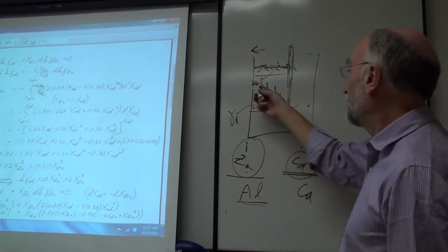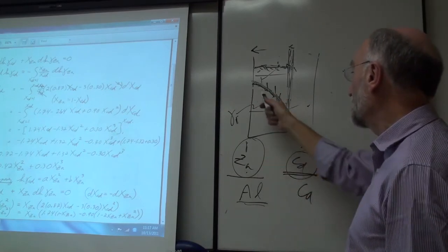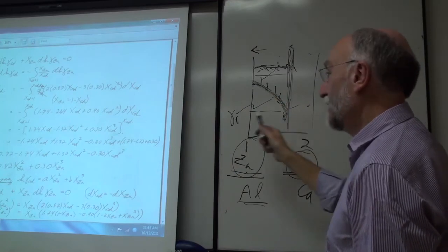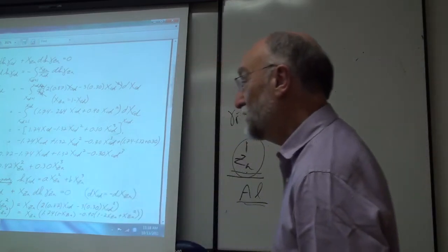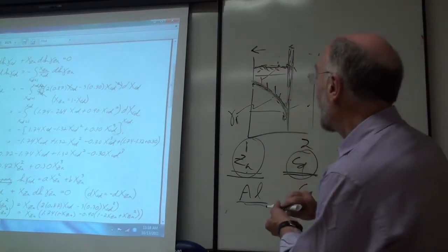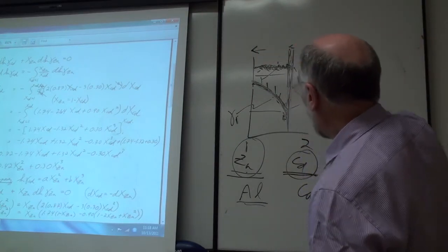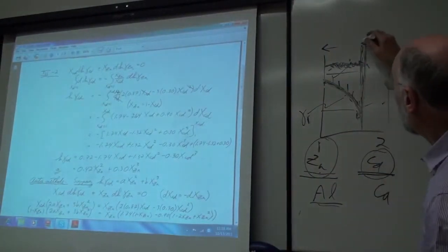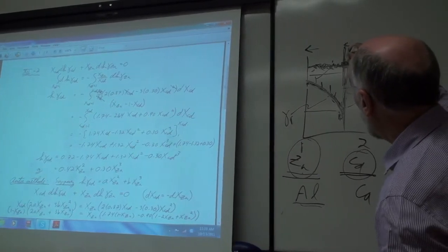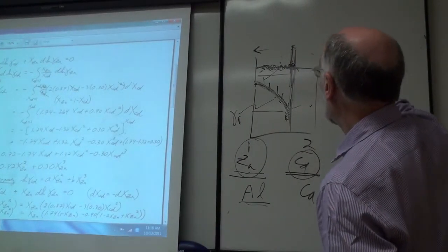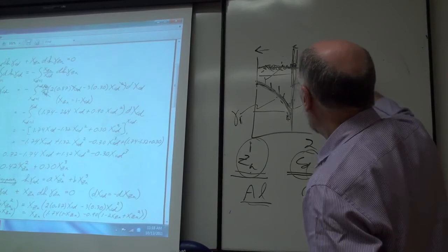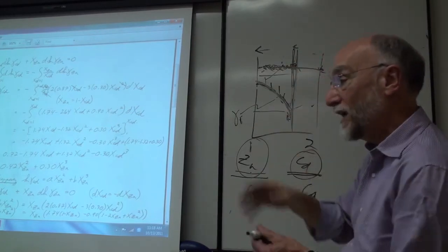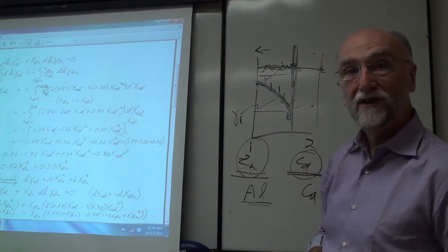Okay, if you fit up this liquidus, say it's the zinc cadmium system, it's giving you the activity of zinc over this region. The equation you get to fit up the activity of zinc then is accurate because it's going through actual experimental points. If you then use that same expression to give you the expression for cadmium, using say even a known endpoint here, or even if you know it all the way over to pure cadmium, you're integrating away from your endpoint towards this end, and the further you integrate, you have cumulative errors when you're integrating an expression.